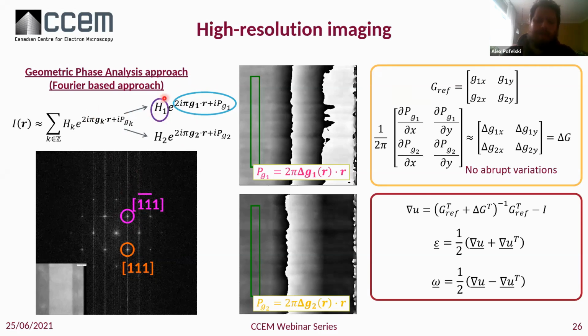We'll have a real and an imaginary component, and you just display the imaginary component here by looking at the phase. And we're going to choose an area that is going to be, say, a strain. So coming back to this definition of a relative strain, Cartesian method, defining an internal reference in the final state, that will be G equals 0, and we will have here the view of the variation of delta G through the entire image.